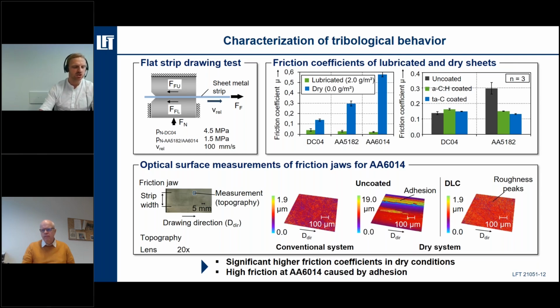Using lubricated sheets, the friction coefficient reaches almost the same level for all material compositions. However, under dry conditions, the friction coefficient varies extremely, which might be explained by different strength of the workpiece and the different contact behavior of the tool material. In order to analyze the reason for the huge deviations between the friction coefficients, a surface characterization was performed after testing, which can be seen here in the lower pictures. By using uncoated tools under dry conditions, adhesive wear locally appeared, which led to increasing friction forces. These are the colored lines which you can see, which we can indicate as adhesive wear.